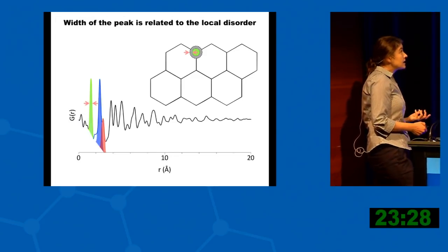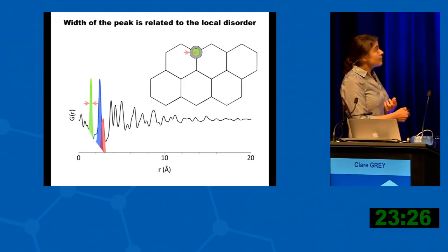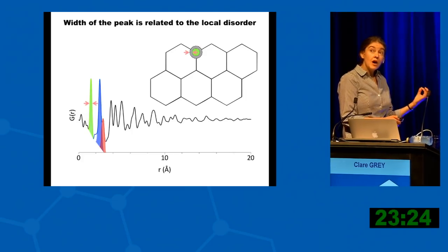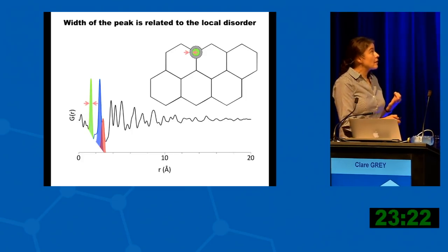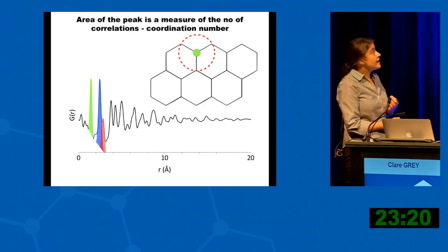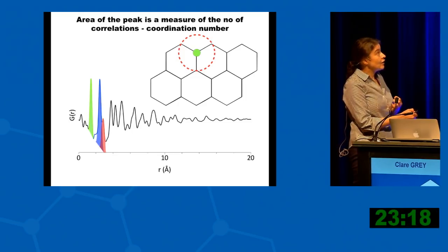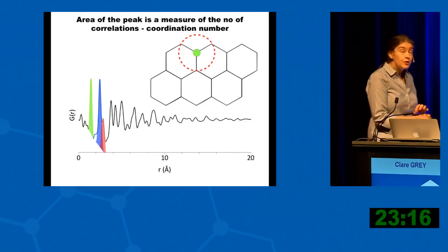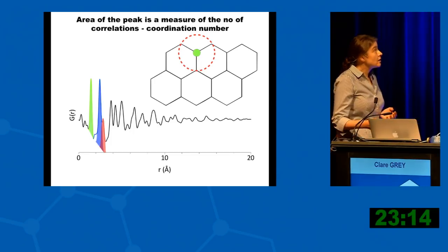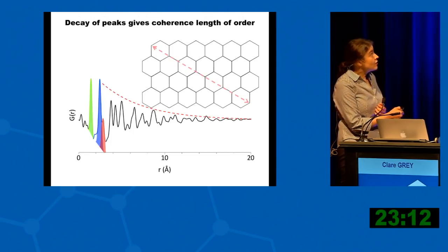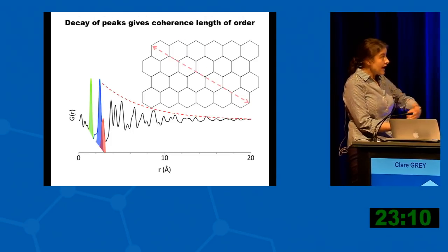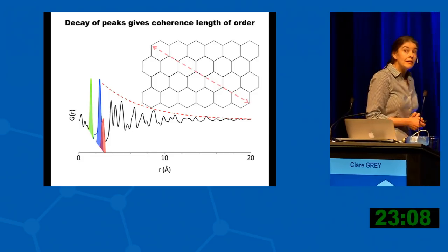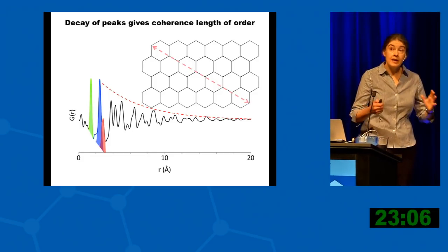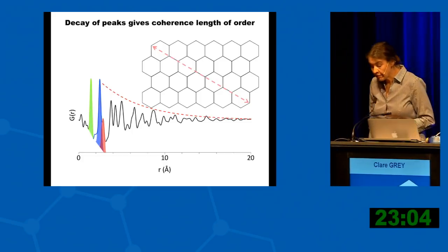And if you analyze this in more detail, the width of the peak tells you the distribution of carbon-carbon distances, so it tells you something about the local disorder. The intensity of the peak tells you how many carbon-carbon bonds you have, so it tells you something about the coordination number. And then the gradual decay of the system tells you about the coherence length, so the degree and length scale of ordering in these materials.